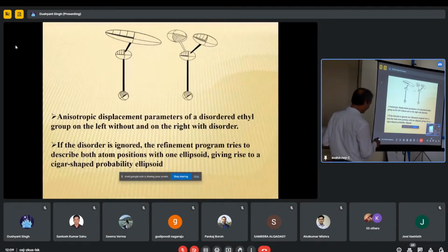So, if the disorder is ignored, the refinement program tries to describe both atom positions with one ellipsoid. You can see from here, giving rise to a cigar-shaped probability ellipsoid. It is not an ellipse. It is a cigar shape. So this is the first-hand information from the ORTEP diagram itself that your structure is showing some kind of disorder.